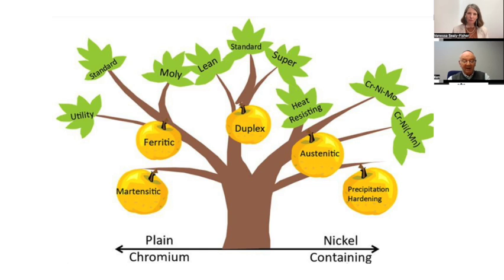So the ferritic stainless steels have useful corrosion characteristics, but a downfall would be their weldability. They don't retain the good strength after welding, and hence they will only be used in thinner sections where any welding that does take place would be much lighter, if we could refer to it in that way, rather than heavy welding passes. So that's from the plain chromium side of the family tree.